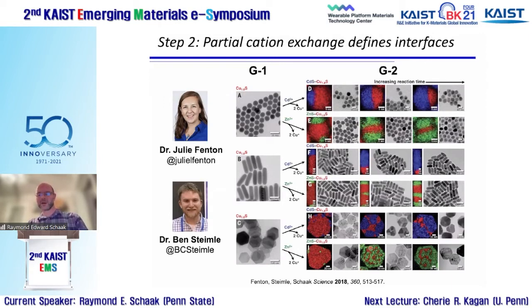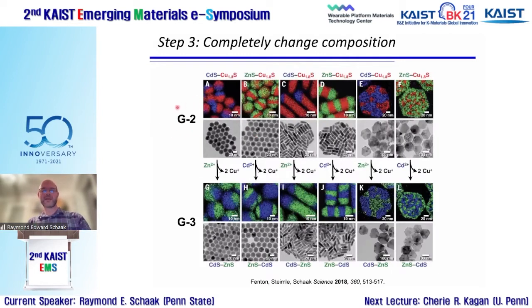And so if you look at this middle column that has the halfway-ish types of particles, we can take these second generation structures and say, okay, for this one where in the second generation we did a cadmium exchange, let's now do a zinc exchange to get rid of the remaining copper. And we end up with spheres that look like the copper sulfide we started with, one half being zinc sulfide, one half being copper sulfide. If we started with the zinc exchange first, we'll go back and do a cadmium exchange next. So we'll make these sandwiches that are zinc sulfide on either end with cadmium sulfide in the middle, and so on. So in the end, we have these third generation particles that maintain the morphology and nanoscale features of the first generation, with the interface defined at the second generation, but have completely different metal sulfide materials in the end.